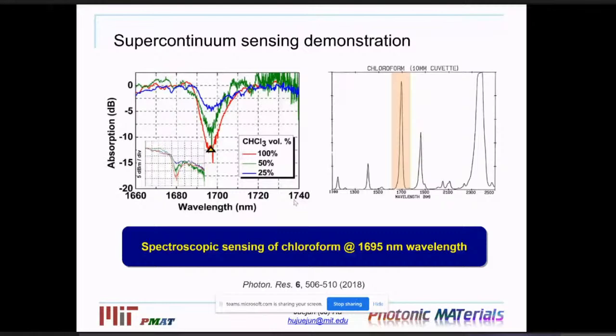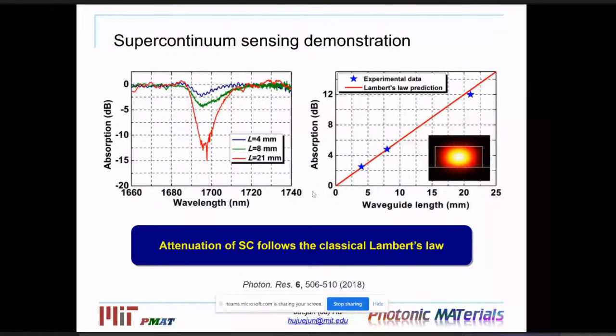So our next step is to use this supercontinuum source to demonstrate sensing applications. For example, we take chloroform as a model molecule, which exhibits an absorption peak around 1.7 microns. Now if we pass our supercontinuum through a medium that contains a chloroform solution, the supercontinuum spectrum now exhibits a little notch that's induced by absorption of these molecules. We can further fit the absorption data to the classical Lambert-Beer's law, and we find that the attenuation of the supercontinuum also follows the classical Lambert-Beer's law. So this allows us to perform quantitative integration to determine the concentration of different chemical species.